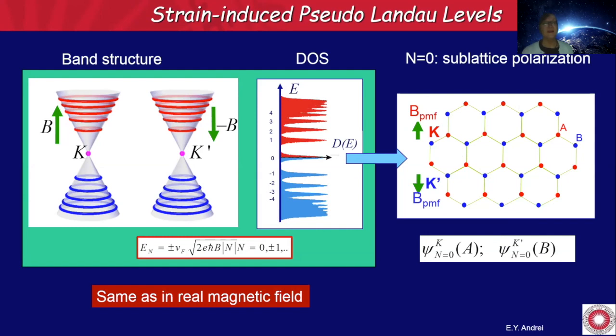So now, since you have a pseudomagnetic field, you're going to create Landau levels. We call them pseudo Landau levels. But the Landau levels and the density of states don't care about the direction of the magnetic field. They are the same regardless of which way the magnetic field points, as long as it is perpendicular to the two-dimensional layer. So we're going to have a pseudomagnetic field pointing up in the K valley and pointing down in the K prime valley. The spacing between the energy levels is exactly the same as you would have in a real magnetic field. And the Landau levels that you'd measure, for example, in a scanning tunneling microscope, the spacing will be the same. So in principle, you couldn't tell the difference.